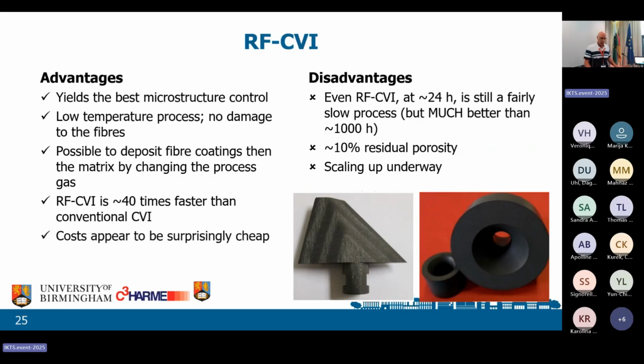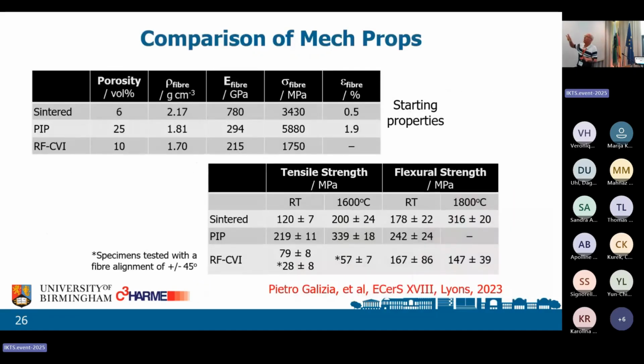Costs appear to be surprisingly cheap. So if we then compare, how do these things compare? Well, you've got the basic materials that you start with, and then you look at the properties coming out. Sintered are very good. Notice how the strengths go up with temperature. Significantly, 120 to 200, 178 to 316. PIP is really quite porous. Look at it, 25% porous. But you're getting much better strengths. We were surprised at that, but that's what came out. RF CVI are the lowest numbers that come through, but they're still perfectly reasonable.